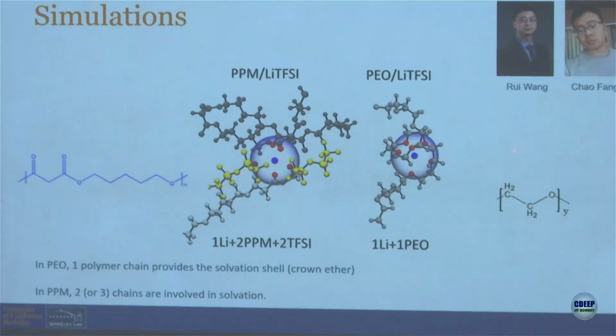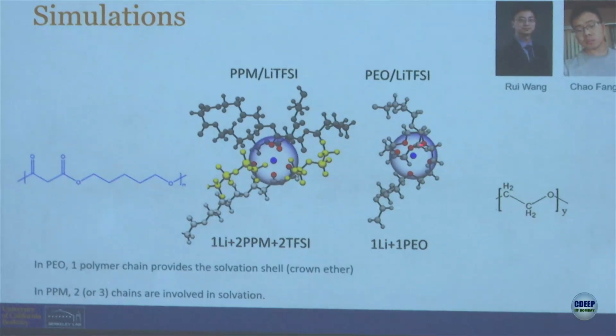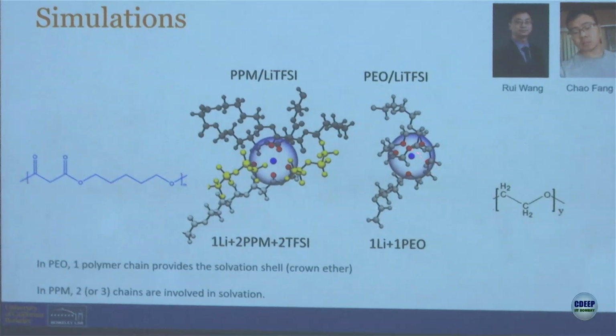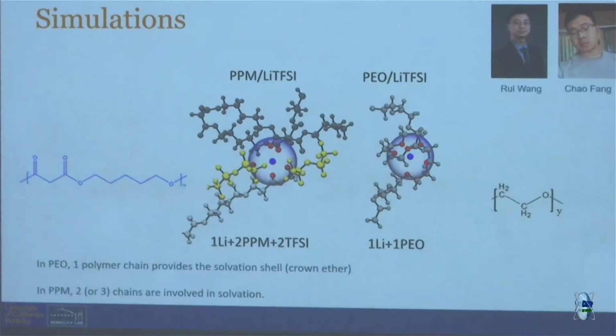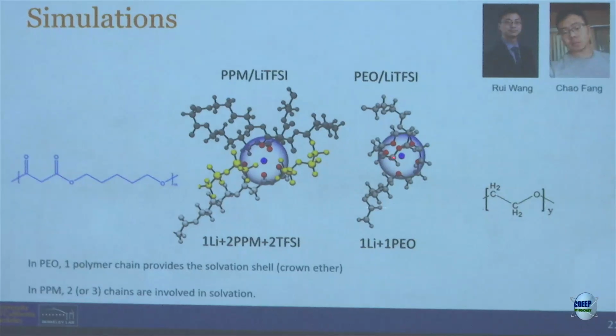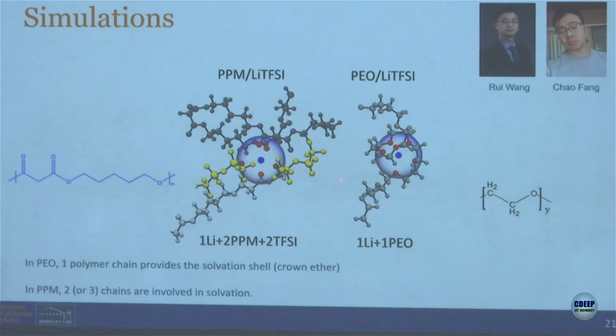Rui Wang joined our department, and as I said, he changed our life. Until then, we had no molecular pictures. So these are typical snapshots of the two polymers. The snapshot of PEO is in the literature. Okay, what happens is if you have a lithium ion, which is this blue thing, you can define its neighborhood like the circle, and these red oxygens, you can see about 6 of them in the neighborhood of this ion, but all of them are donated by one chain. And this is well known in polyethylene oxide. It's a beautiful structure.